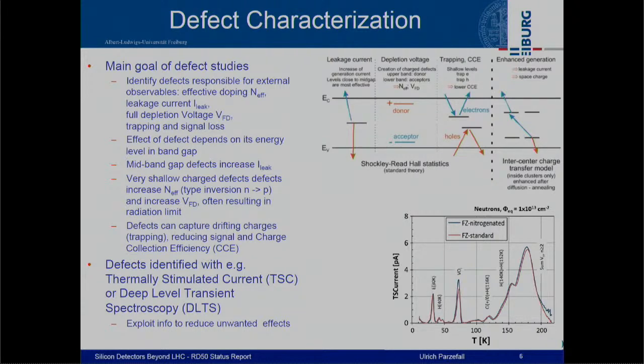For example, the leakage current mostly comes from mid-band gap defects. And if you look at the change of the depletion voltage, which comes from the change of the effective doping concentration, this is caused by defects which are very close to the band edges.